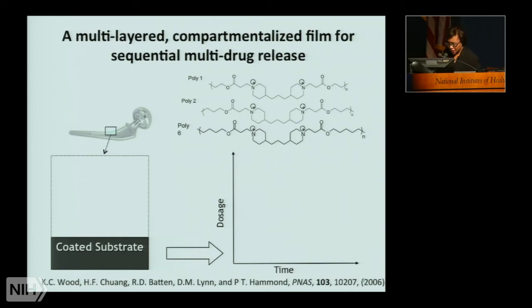On top of that, if we think about a more traditional polymer like polylactic glycolic acid as a carrier, this polymer would allow you to put in about 1 to 2 weight% of a material system like a drug. Then the rules of thermodynamics take over and you're going to get phase separation because all polymeric systems can only contain small amounts of another material before you get phase separation. And if you get phase separation, you're going to get a bolus release, everything coming out at once. On top of that, if you put 2, 3, or more drugs into a conventional coating, they're all going to come out at once.